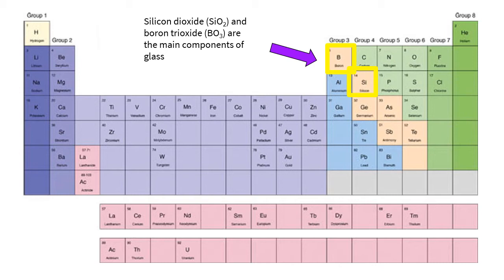So Pyrex has an advantage because it doesn't shatter with thermal shock. When glass is made with just silicon dioxide, if you heat it and then cool it, it will break. So borosilicate glasses like Pyrex are much more resistant to thermal shock. And they do need to be in the right combination in order to get that maximum benefit. So that's the main component of our glaze, that glass former, a combination of silica and boron.